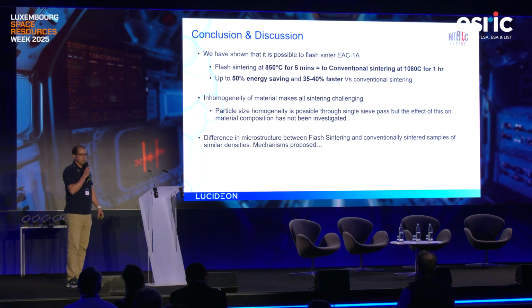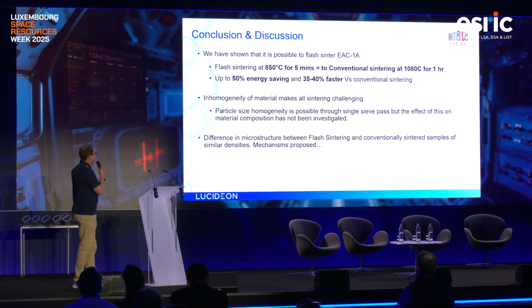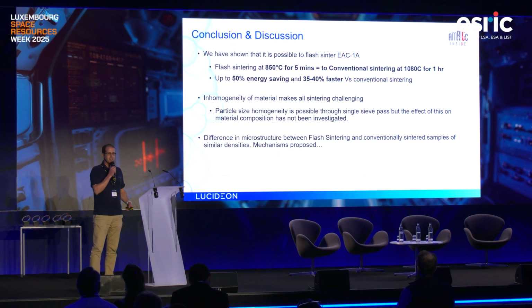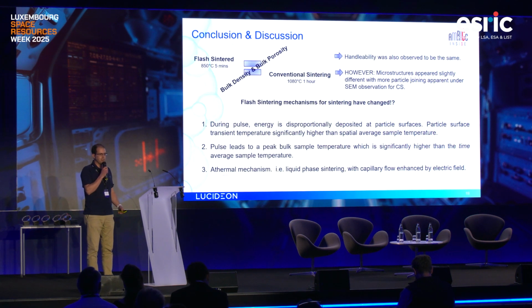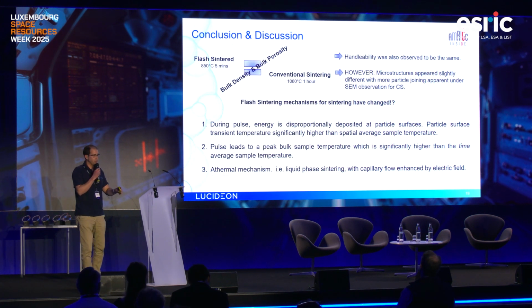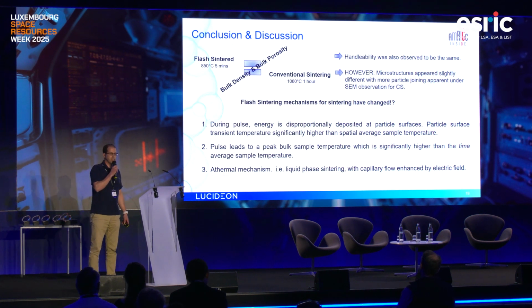But the inhomogeneity of any regolith material makes sintering challenging, whatever technique is used. We didn't have time to investigate any sieved material and improving the homogeneity of the pressed material in the first place. That's something we could look at. But looking at the different microstructures, the handleability and the density were the same, but we did see more particle joining under SEM observation only, so we could zoom in a bit further in the next stages. There was more particle joining for conventional sintering. So we're proposing that potentially the flash sintering mechanism may be different. This could be an athermal mechanism, i.e. liquid phase sintering. We're kind of igniting that glass phase and gluing everything together, in which case adding more glass phase, as a previous talker was saying, could be quite beneficial.